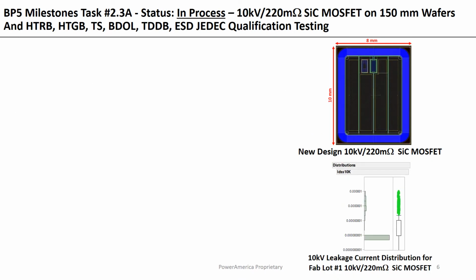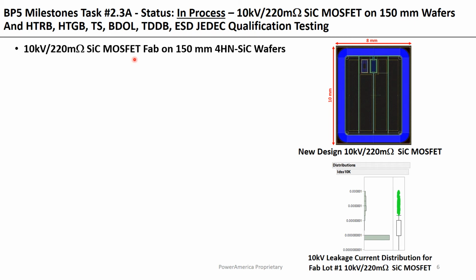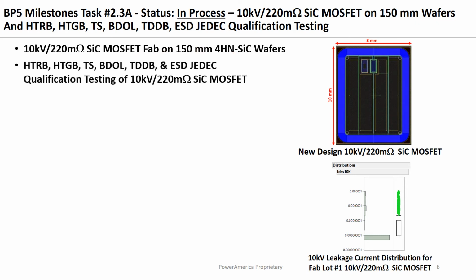For the BP5 task, there are two major groups of tasks. One is fabrication of 10 kilovolt, 220 milliohm silicon carbide MOSFETs on 150 millimeter wafers, and then JEDEC qualification of these 10 kilovolt, 220 milliohm silicon carbide MOSFETs, including HTRB, HTGB, thermal shock, BDOL, TDDB, and ESD.